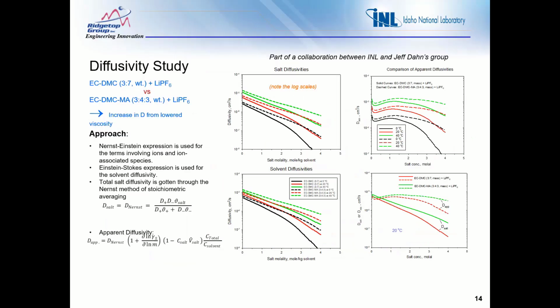Okay, just thought I'd show a little more granularity for some of the terms. For diffusivity, the overall approach is a Nernst-Einstein expression that's used for the different ionic and ion-associated species. So every species that's calculated and determined to be present due to thermodynamic equilibrium has diffusivity values calculated for it. When it comes to the solvent, we use an Einstein-Stokes expression. The total salt diffusivity is gotten through a Nernst stoichiometric average, given there in that first equation.